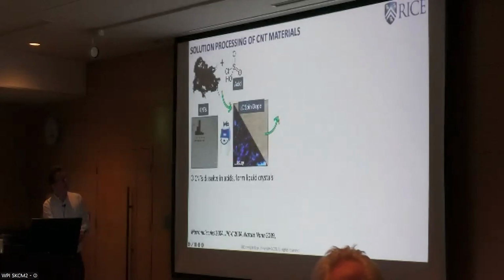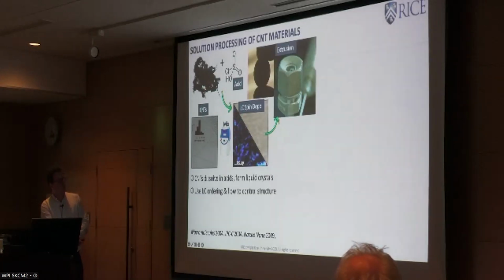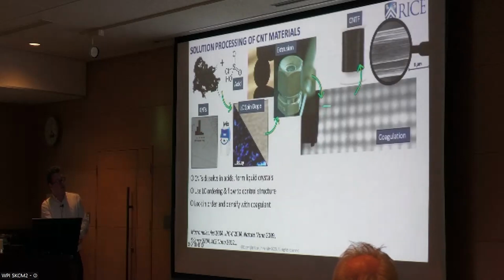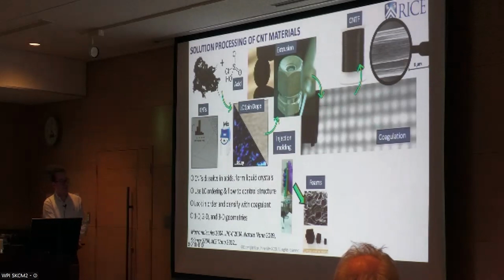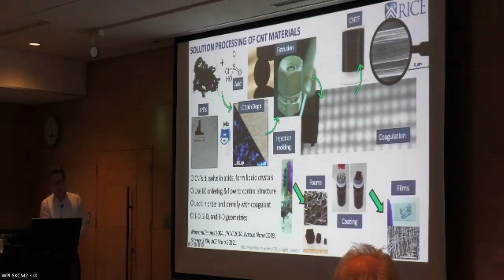And then what you find out is that sulfonic acids are solvents, and if you go to high enough concentration in sulfonic acid, you can make liquid crystals. And once you have liquid crystals, you can spin them much like the way you would spin Kevlar or other polymers and make fibers. You can also make foams by putting them into shapes and removing the solvent, or you can make films. And so you can make materials.